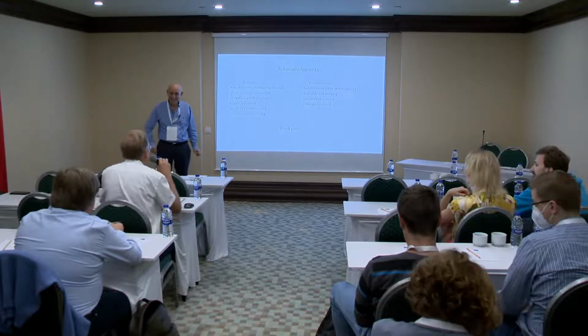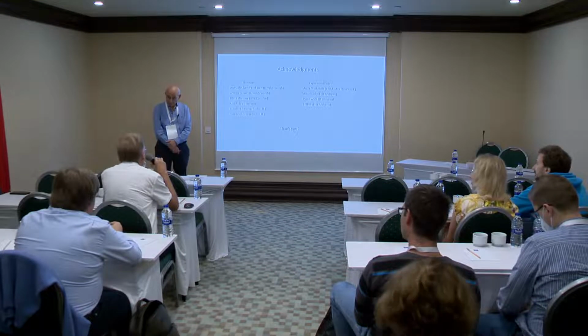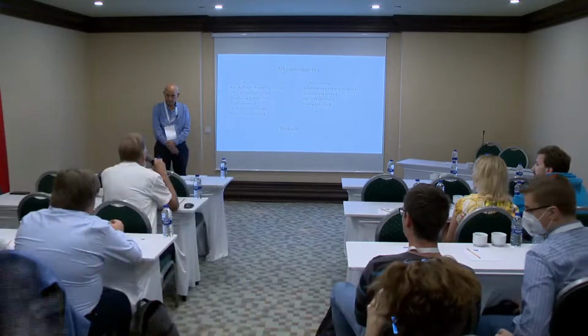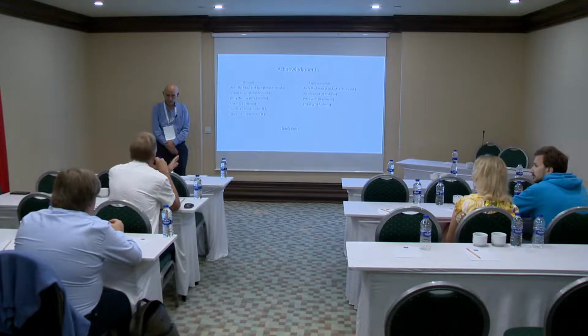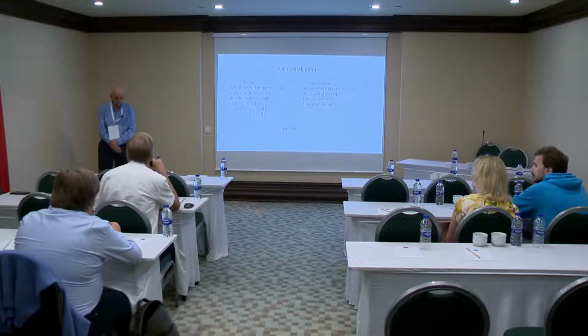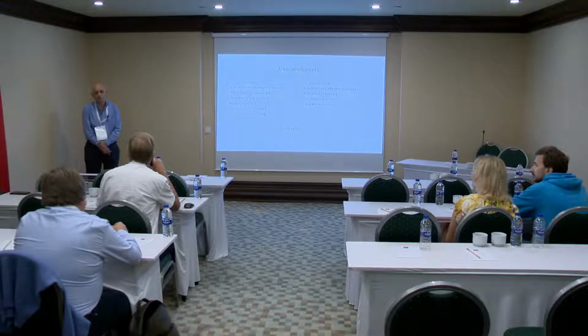So just for my understanding, so that I don't misunderstand something of your conclusions. In your DFT calculations in all this bilayer ruthenate, you mimic the application of an external magnetic field by introducing some magnetization per unit cell. Does it have some relation to the magnetization that is measured experimentally, so that there is some proportionality, say you apply a field of 5 Tesla and you get a magnetization of, say, 0.3 Bohr magneton per ruthenium, or is it something artificial? And the sub-question is, you observe a topological transition, right?